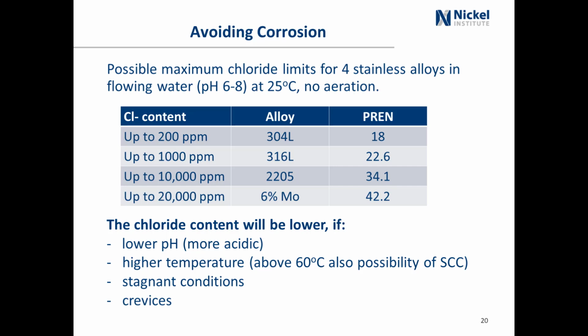And the PREN really, like I said, it only just gives you a ranking, because it doesn't help you identify whether a particular stainless steel is going to be resistant in a particular environment, because we can look here and you see the PREN for 304 is 18 and 2205 is about double that, but it can handle about 50 times more chloride than 304L. So the PREN is just simply a means of ranking materials.